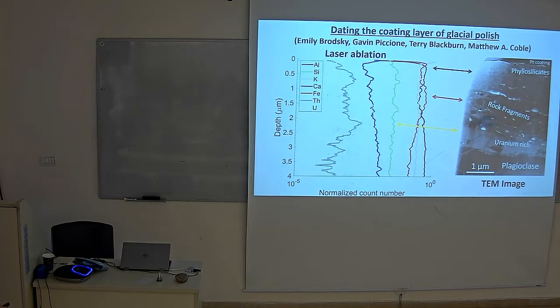We can see the chemical composition changing in the iron composition, so maybe it reflects the phyllosilicate layer and some concentration of iron oxide in this layer, and then in the rock fragments there is an increase of the iron. However, what is important is we are getting more uranium in the inner, amorphous layer inside here, and that may allow us to use the uranium-thorium method in order to date it.